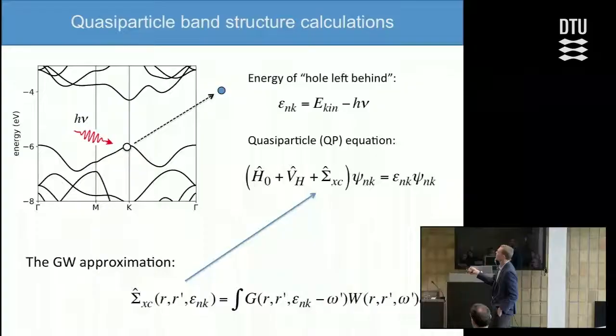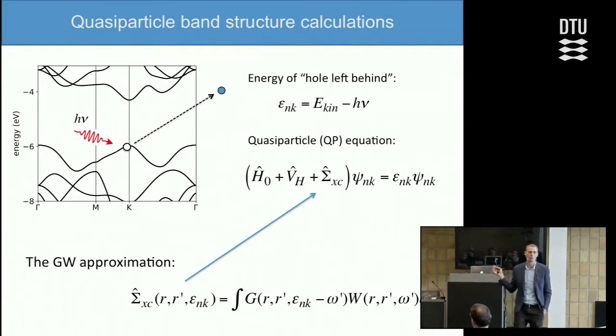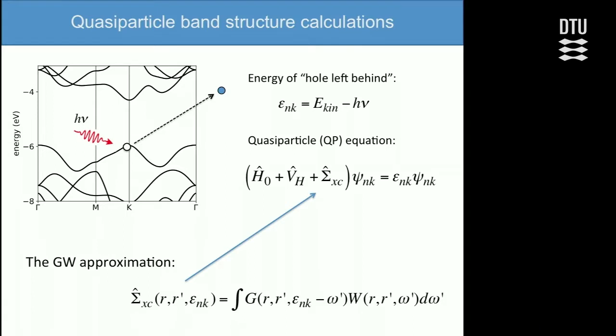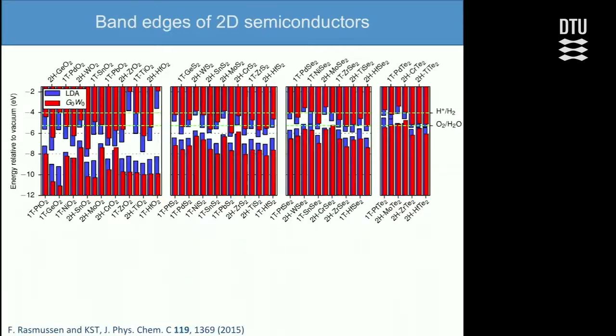That self-energy, in the widely used GW approximation—which has been used throughout the thesis—takes this form mathematically. What I want to show you here is that the screened interaction between electrons enters explicitly in this expression. This shows that by manipulating the screened interaction, we should be able to manipulate the self-energy and thus the band structure of the material.